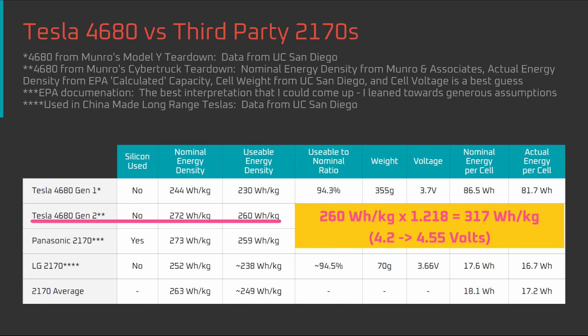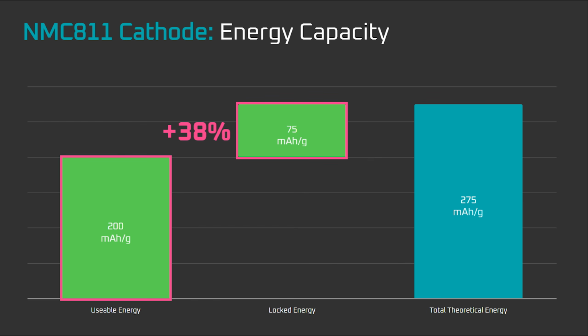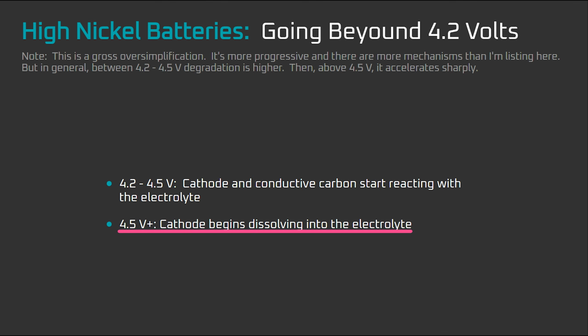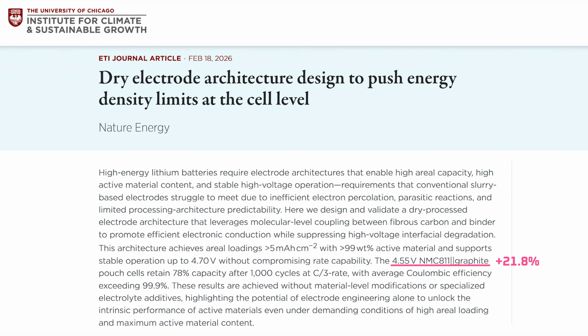A 21.8% energy density increase is, of course, well short of the theoretical 38% possible at higher voltages, but that may never be possible because the cathode dissolution accelerates above 4.5 volts. With that said, the 21.8% energy density increase was reached with a basic cathode and anode chemistry, NMC811 and graphite. Even a small amount of silicon, which is standard in many high-nickel battery cells, would add about 10% to the energy density.